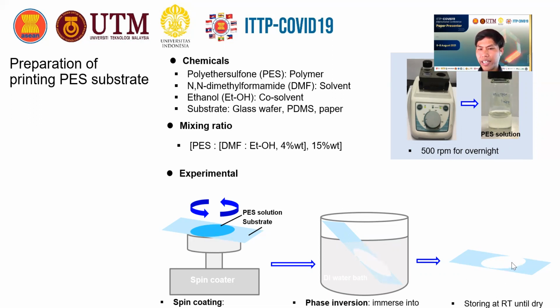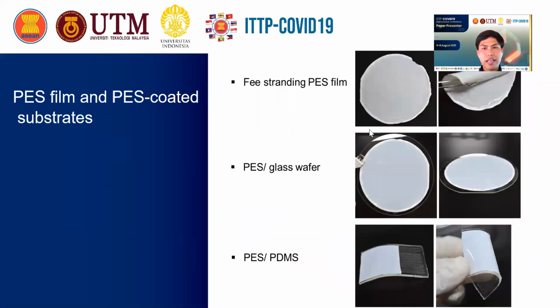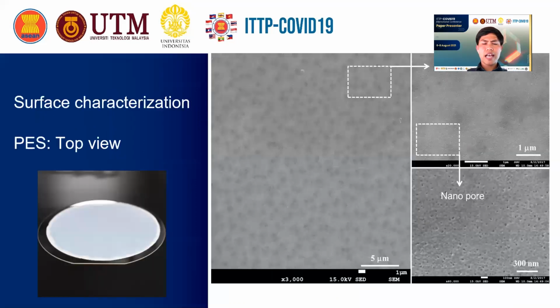Finally, we get the thin film polymer, and dry it at room temperature. And you can see here, we can achieve a freestanding film or a coating film, or even coat it on a flexible substrate like PDMS. With that, we then characterize the top surface.